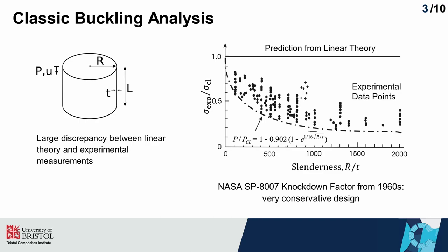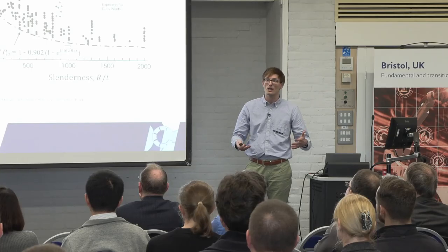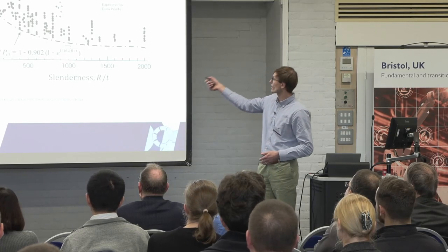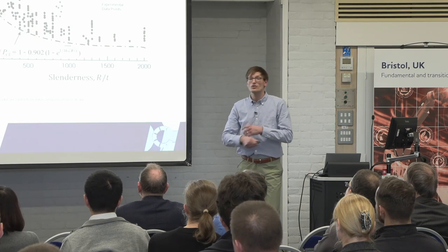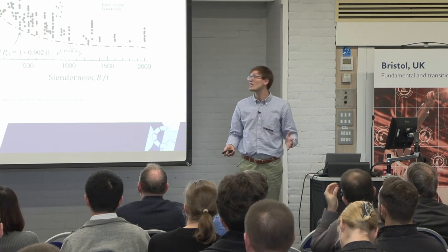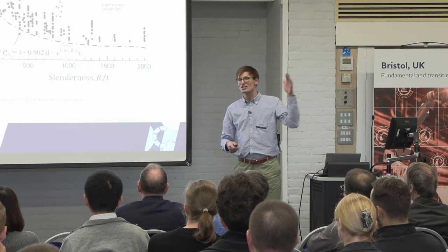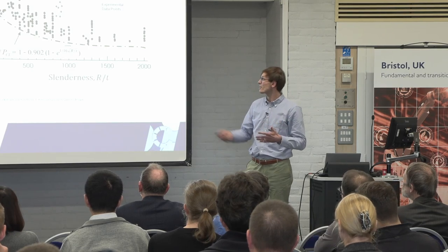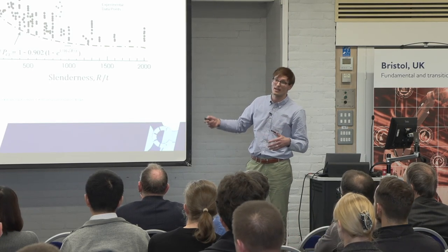this is a very, very famous plot in the space structures community. If you have a thin-walled cylinder of some radius, thickness, and length, we can compute analytically what the expected buckling load is, and that's the horizontal line at the top here. Now, if you do any form of experiment, you will very quickly realize that the cylinder actually never reaches that buckling load, but fails sometimes at up to 20% of that expected load.